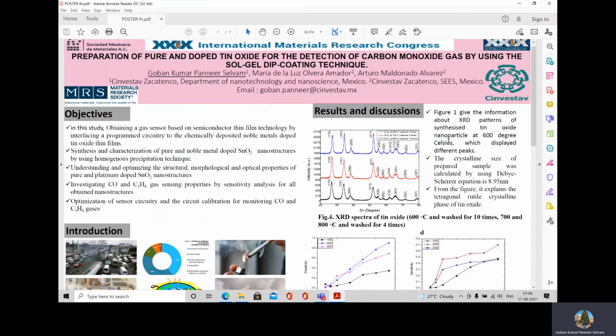In the results, first I'm going through the XRD. The XRD shows the peaks 110, 101, 200, and these are the peaks which show that tin oxide is formed. The peaks 110, 101, 200 match the reported values of tin oxide in JCPDS.